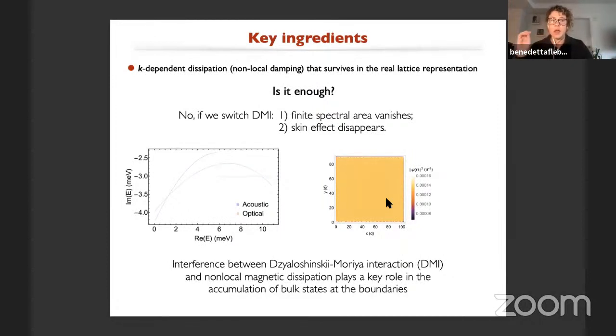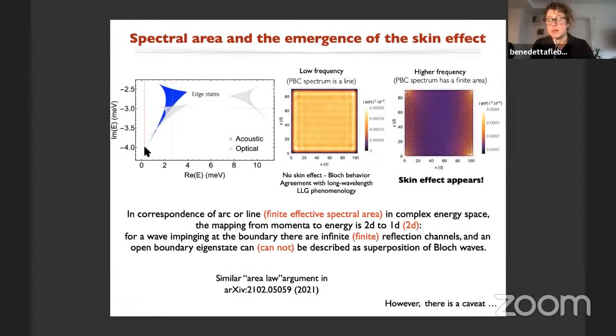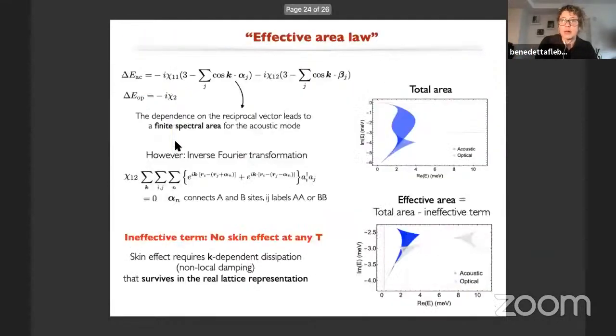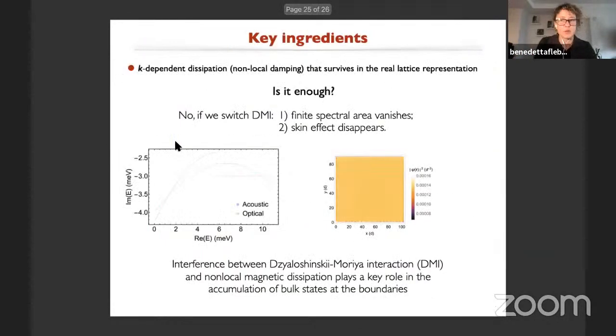First of all, we need a K-dependent dissipation, some non-local damping that survives the real lattice representation, so that even when the Fourier transform is done, it is still there in the real lattice Hamiltonian. Why does it need to be K-dependent? Because if it's just a K-independent term, like the usual Gilbert damping in the LLG phenomenology, it will just be a line. So there is no area, and the skin effect is not going to emerge. So we need this non-local type of dissipation.